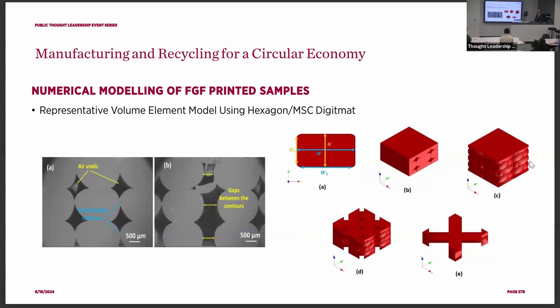For the RVE model, the full model is lengthy and difficult to create, and for the simulation we are not able to capture the detailed microstructures. So that's what we did: microstructural analysis using SEM. And then we found the gaps between the contours, the air voids between the infills. Then we created representative volume element models, that is the RVE model. For different cases, different infill, that is 40, 70, 100%, we have different models.